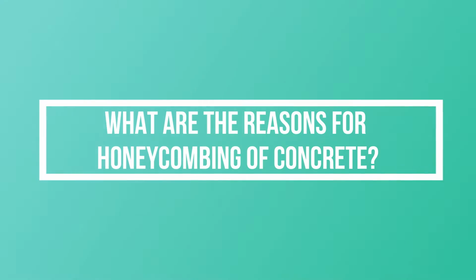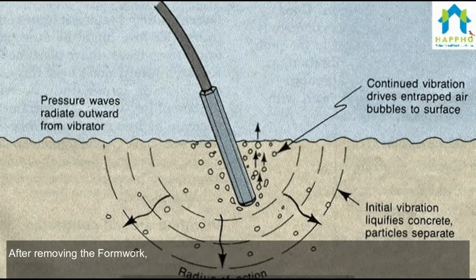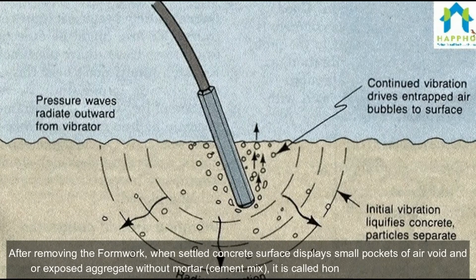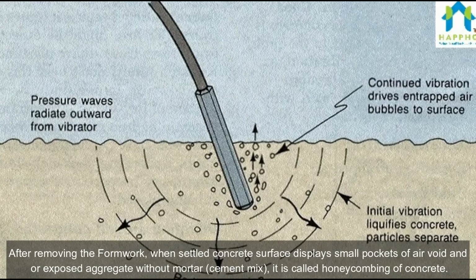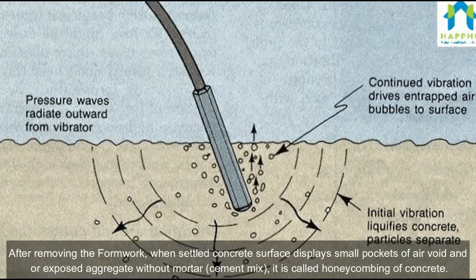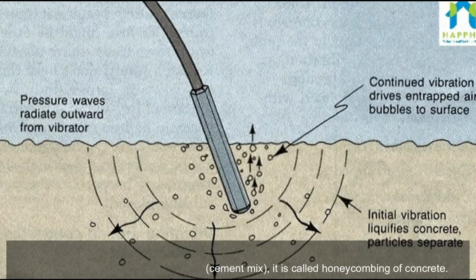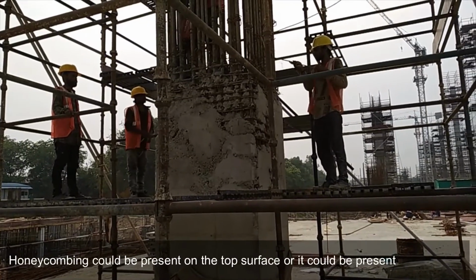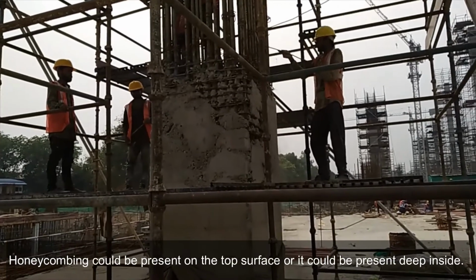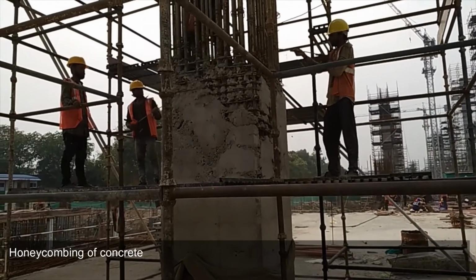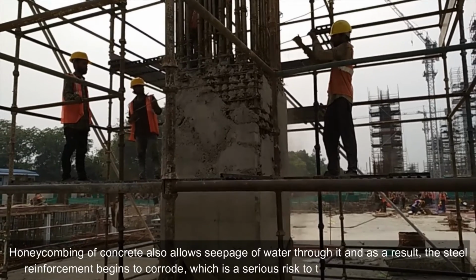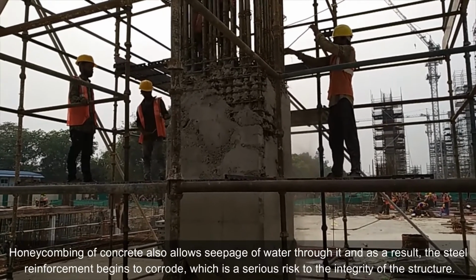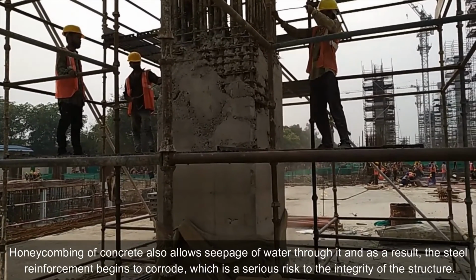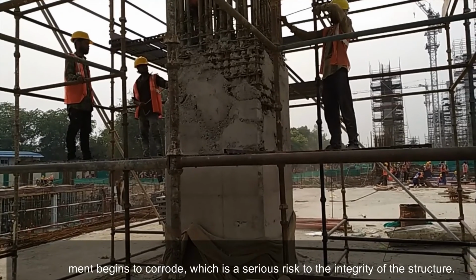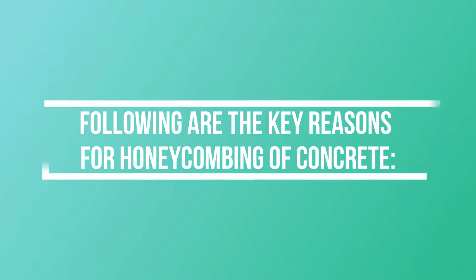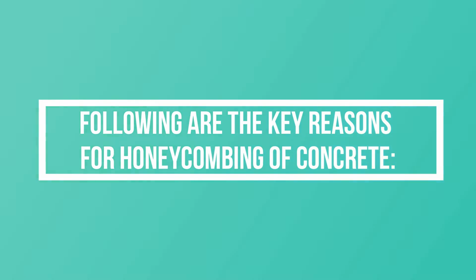What are the reasons for honeycombing of concrete? After removing the formwork, when the settled concrete surface displays small pockets of air voids and/or exposed aggregate without mortar cement mix, it is called honeycombing of concrete. Honeycombing could be present on the top surface, or it could be present deep inside. Honeycombing of concrete also allows seepage of water through it, and as a result, the steel reinforcement begins to corrode, which is a serious risk to the integrity of the structure. Following are the key reasons for honeycombing of concrete.